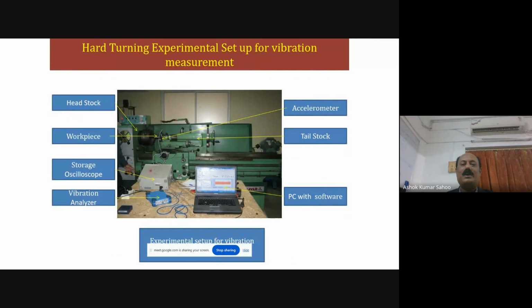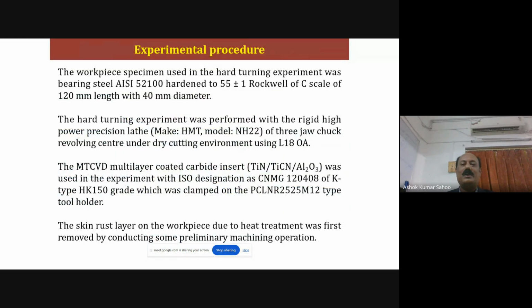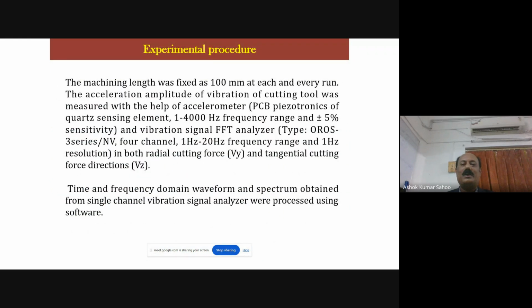This is the experimental setup where the accelerometer is mounted at the tool holder in both the radial direction and the tangential direction. The signal from the accelerometer in the Y direction and the Z direction attached to the tool holder is processed through a storage oscilloscope and vibration analyzer connected with the PC and analyzed with the software. So we capture the acceleration amplitude of vibration in time and frequency domain directly through the vibration analyzer with the PC, for which the machining length was fixed at 100 mm at each and every run.